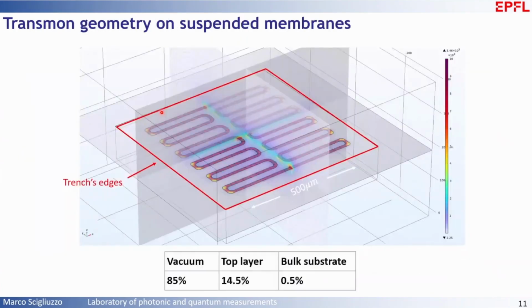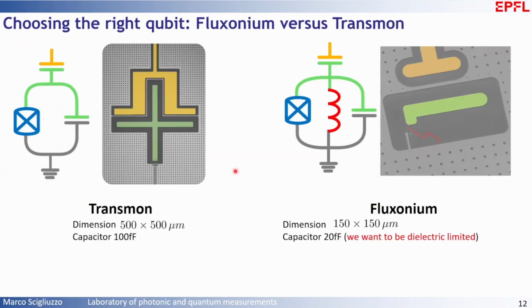So since we can maximally suspend 500 micron, this trench edge is indeed 500 by 500 micron, our transmon will have a shape that looks like this. So now the gap here is around 10 micron. That should still give very high coherence, but nevertheless, we decided to not go for this route.